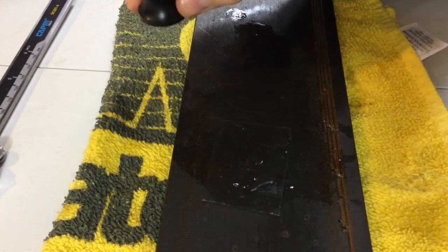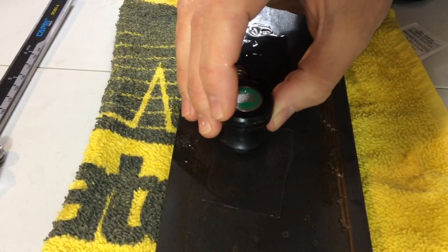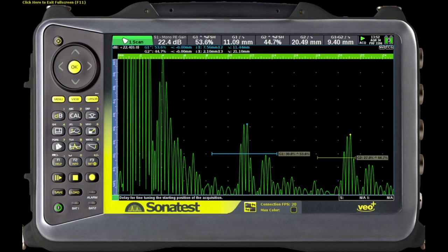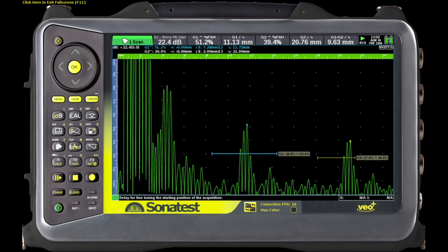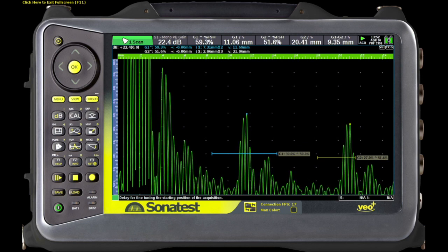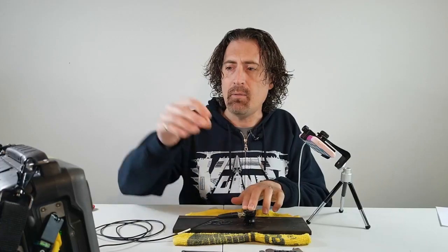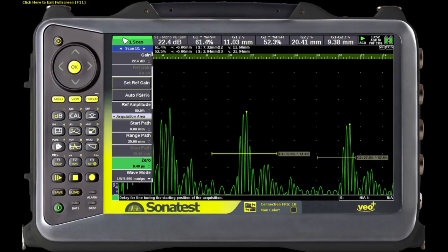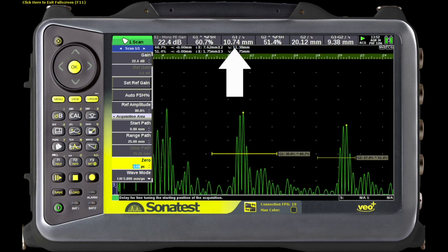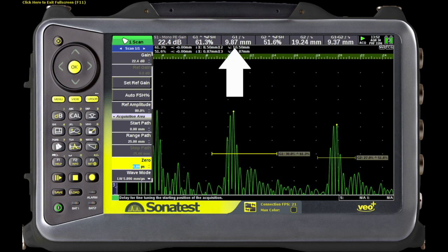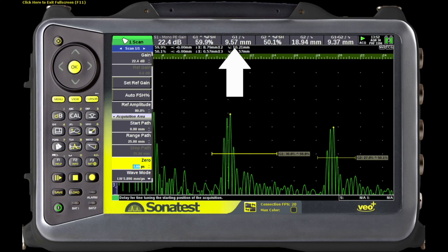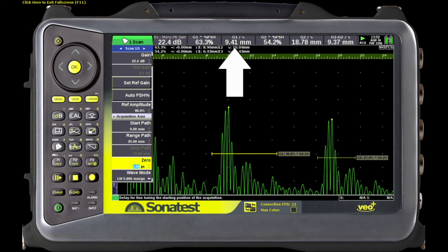So what you want to do is take your probe and put it on an area nearby the really bad corrosion spot that you're trying to measure, in an area that's hopefully free of corrosion. And then take a look at your echo-to-echo reading, and then manually compensate for paint thickness by dialing the zero up so that the gate one reading equals the echo to echo. In this case, I'm gonna turn it up to about, that's close enough. So basically you'd be correcting for coating thickness in real time, assuming that both areas have the same condition. That isn't always the case.